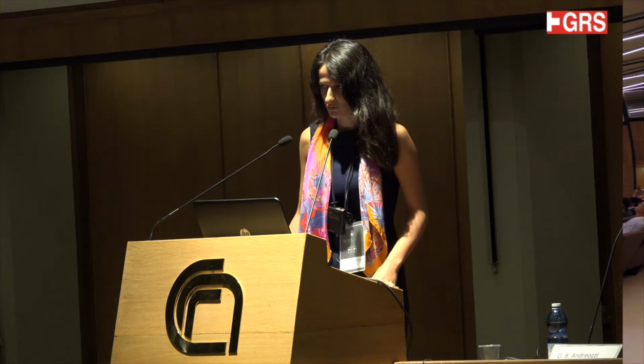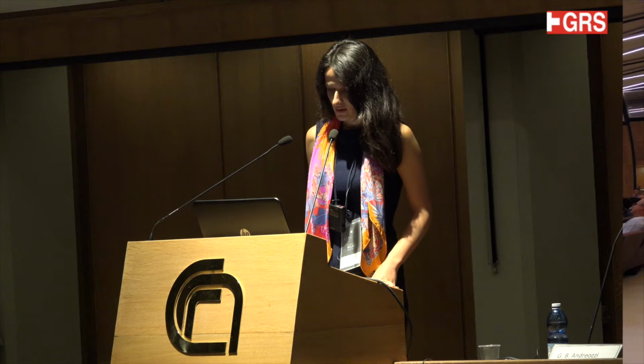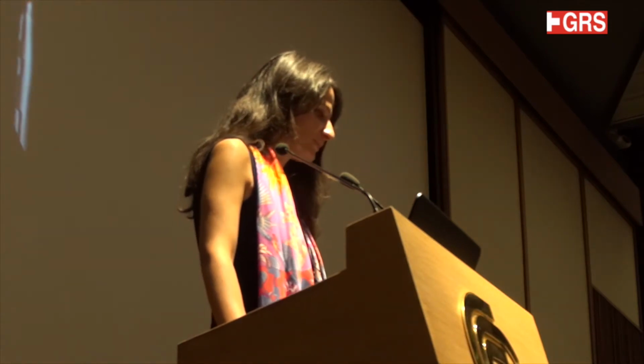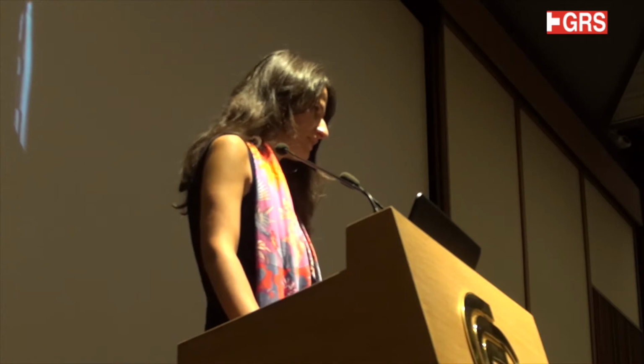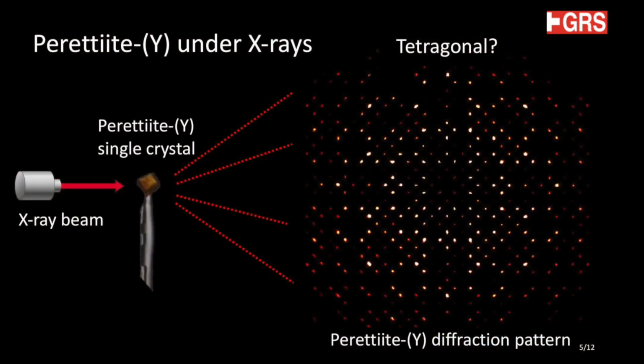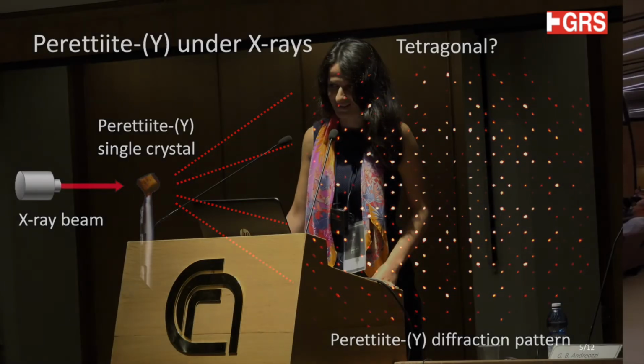But now let's try to answer the second question. What are these yellow needles? To answer this question, we of course performed single crystal X-ray diffraction. We had very little material, so I could mount a crystal of around 200 micrometers on a glass needle. And what we obtained is a diffraction pattern that clearly tells us that these crystals have tetragonal symmetry. Please note that even at high 2 theta, there is no splitting of the reflections, indicating that there is only one option, that the crystal is tetragonal.